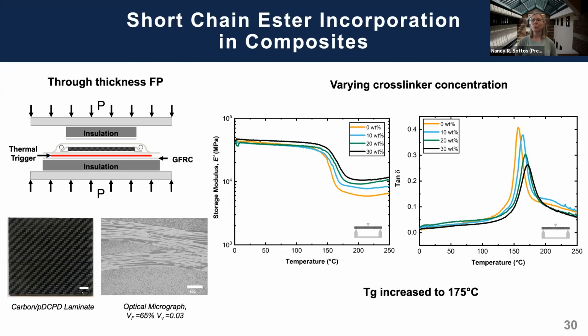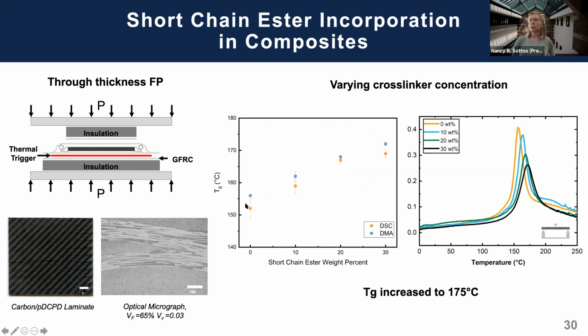But again, we chose to go with the through thickness curing method. And you can see, again, the DMA summarized for the composite on the right-hand side, that by increasing the amount of cross-linking agent, we get our changes in glass transition temperature of the composite. And so we're able to push up our TG of the composite from 150 and approximately 155, 158, all the way up to about 170 for the composite.